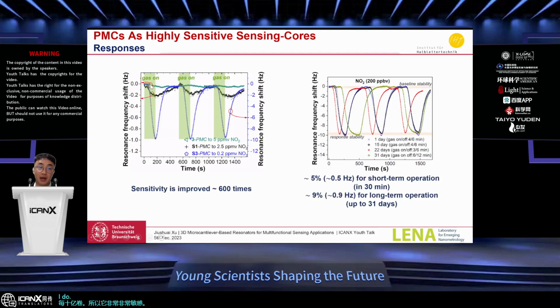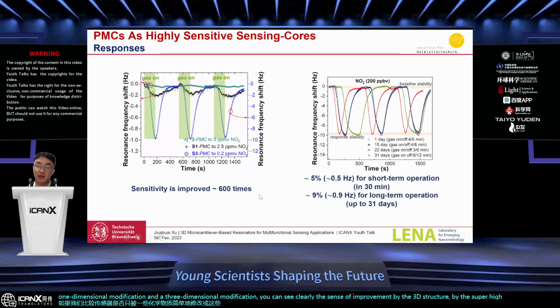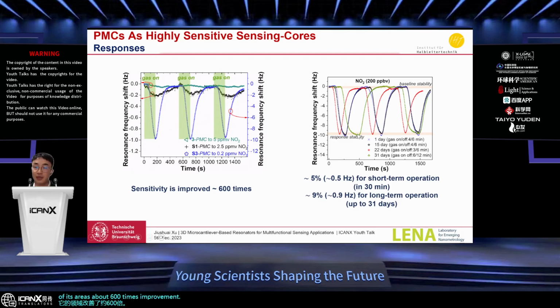And if we compare sensors that have been only simply modified by some chemicals, or with one-dimensional modification and three-dimensional modification, you can see clearly the sensing improvement by the 3D structure, by the super high surface area, about 600 times improvement. And if we measure the sensor at different times with different conditions, we found that for 31 days, very stable signals can still be found.